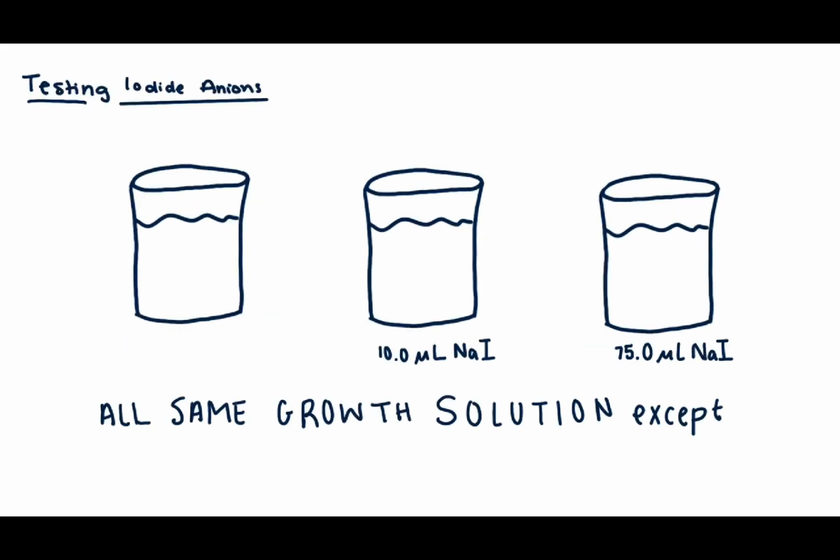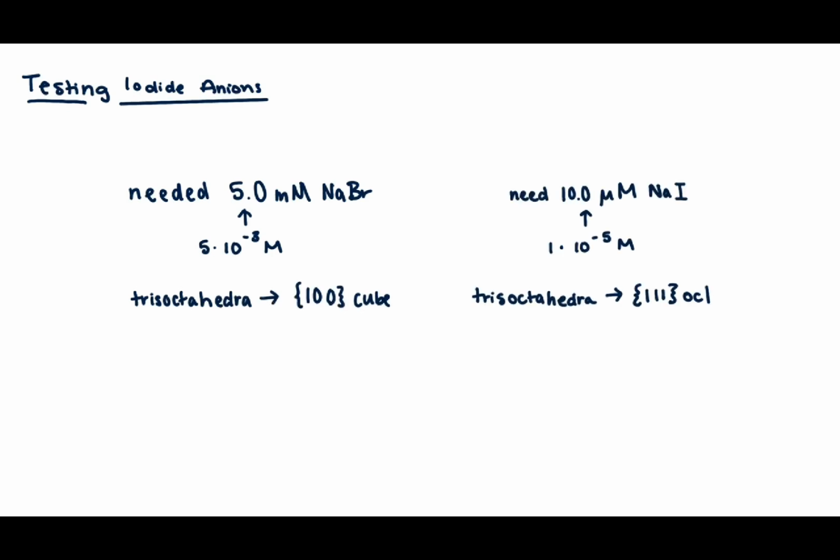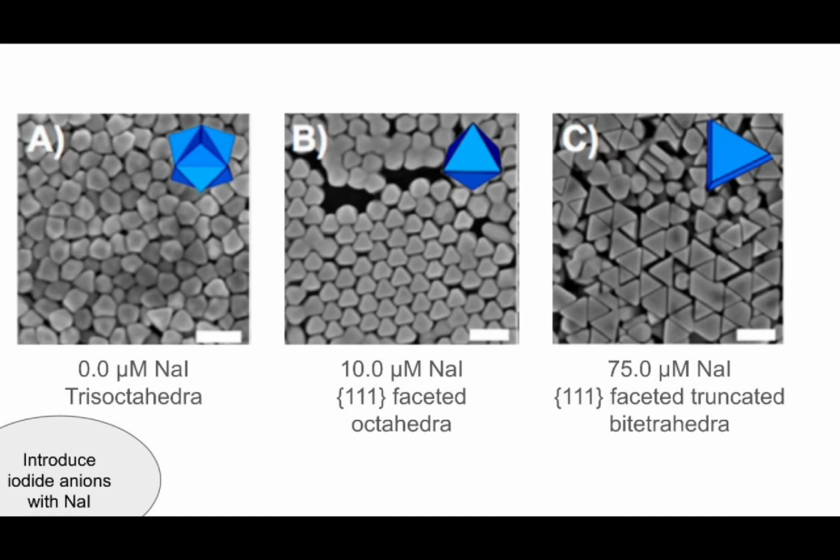However, the amount of iodide necessary to result in similar or greater decreases in rate is 2 magnitudes less than the amount of bromide needed. This relationship also supports the hypothesis that larger halides hinder the rate more significantly than smaller halides.